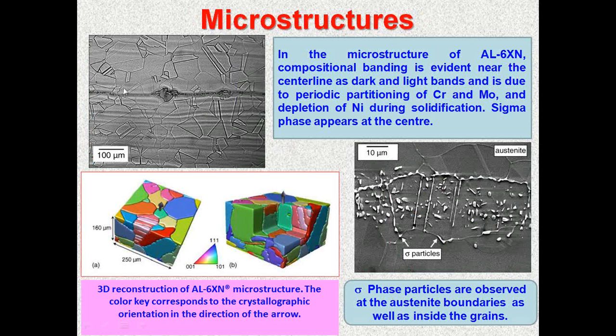And it has a typical austenitic structure, but they also have some kind of compositional banding, where the partitioning of chromium and molybdenum takes place, and because of the high chromium and other alloying elements, it has a tendency to form the sigma phase. And you can see an austenite boundary with a decorated sigma here, courtesy of the website. You will find in the internet this kind of works reported. It has very good application. The corrosive, including corrosive food and beverage products, chemical, cosmetic, brewery, desalination, semiconductor, aerospace, biofuel, pulp and paper, and gas handling applications.